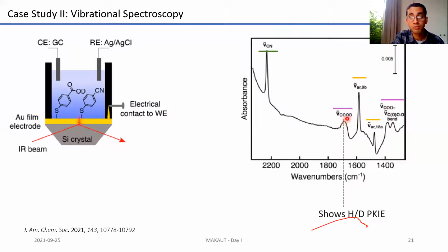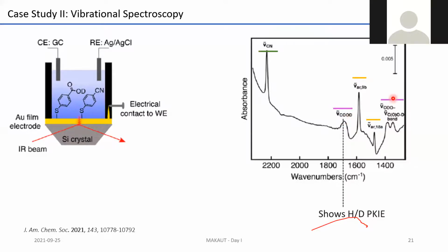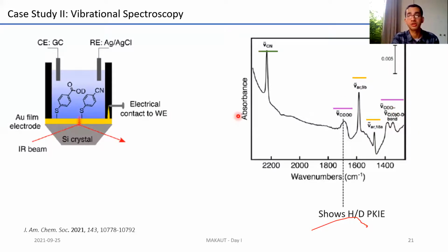Note that the protonated carboxylic acid appears at a different frequency from the deprotonated carboxylic acid. So again, there's proof that IR spectroscopy is essentially used for studying functional groups as well as subtleties associated with functional groups such as deprotonation and protonation. And these are vibrational modes associated with the benzene ring. A real life example of IR spectroscopy used to solve a research grade problem.